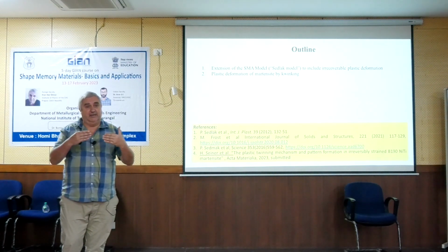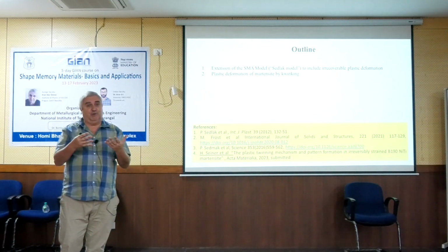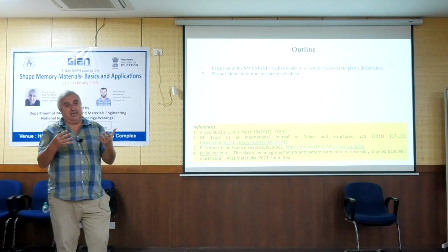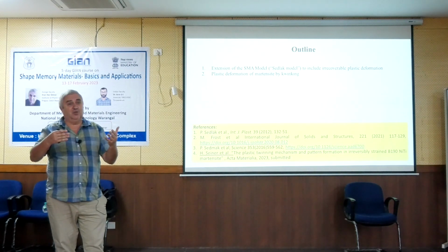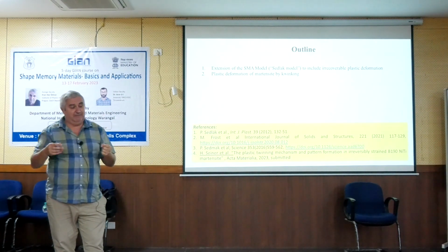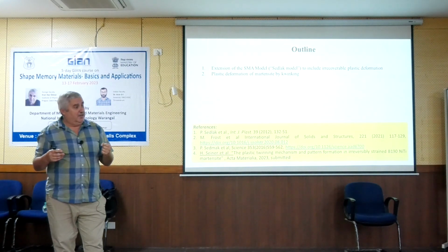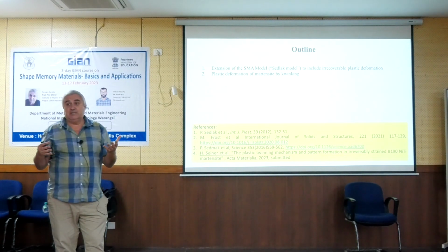You know, as I said, the martensitic transformation proceeds by nucleation and motion of interfaces. The plastic deformation of martensite, based on the results of these TEM experiments, also proceeds by nucleation and propagation of interfaces. It's not an interface between austenite and martensite, but an interface between martensite and martensite, an intermartensitic interface. And realizing this, there is a good chance to develop some